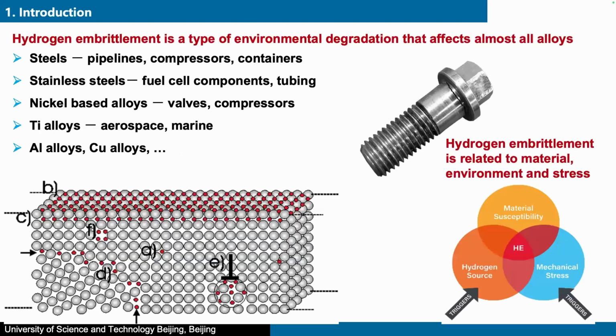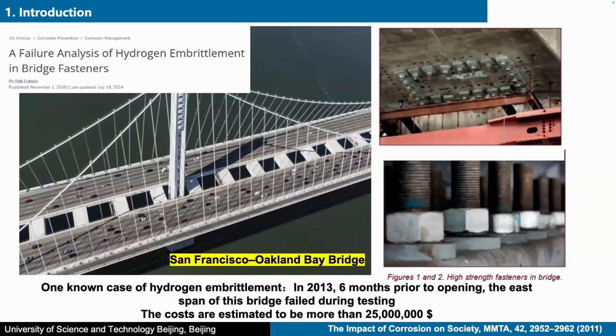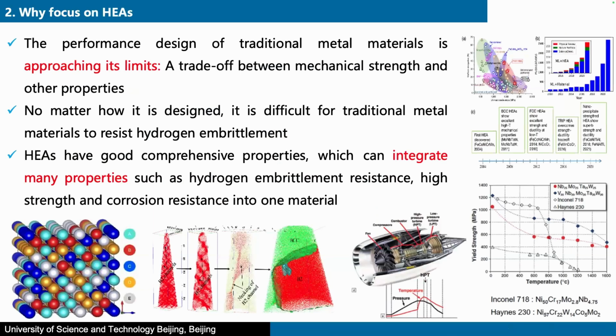First, as we all know, hydrogen embrittlement is a type of environmental degradation which can affect almost all alloys, such as steels, stainless steels, nickel-based alloys. This is one very well-known case of hydrogen embrittlement: the San Francisco Oakland Bay Bridge. We did some testing and found high strength fasteners suffered from hydrogen embrittlement, and it caused a lot of economic losses.